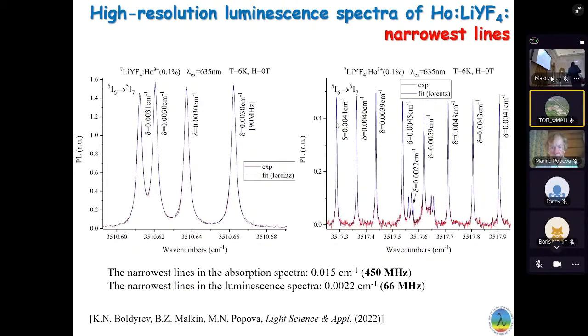And what's interesting and surprising for us, in the luminescence spectra, the line width of the observed hyperfine structure is much narrower. In the absorption spectra, the narrow lines are 0.015 wave number, around 450 megahertz. But the narrowest lines in the luminescence are 0.0022, which is 66 megahertz. So this is the narrowest luminescence observed from an ensemble of atoms in the crystal.